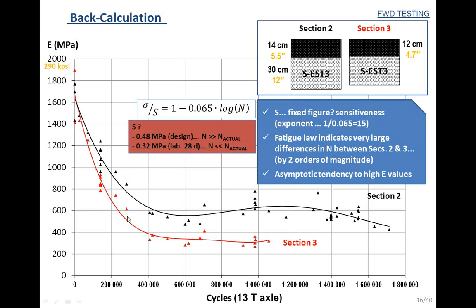When you see this performance, it seems like the modulus has decreased similarly in the 2 sections. The other thing is that at the beginning of the test, we were assuming this tensile strength, because this is the typical value that people think here in Spain for this material. This value represents the long-term strength of the material. But if we introduce this value in this formula, we would obtain a fatigue life much larger than the fatigue life we have seen in the test track. On the contrary, if we use 0.32 megapascal, the value we obtained from laboratory testing after 28 days, then N would be much smaller than the fatigue life we have seen in the sections.